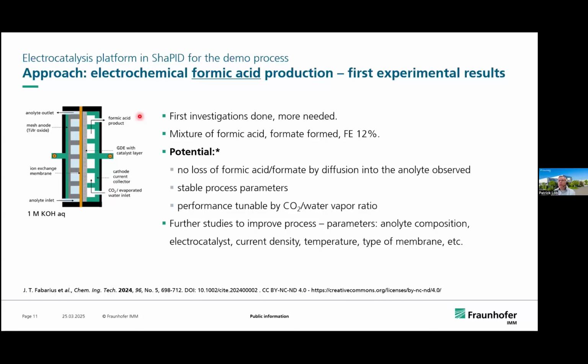We produce formic acid and formate in high concentration without salts, and we underlined the potential. We have seen no loss of formic acid or formate by diffusion into the anolyte. We have stable process parameters. We see that we can influence the performance of the cell by tuning the CO2 and water vapor ratio. And it's clear that with a Faraday efficiency of 12%, we have to make further studies. But for this, our reactor is now in place and our settings are done.